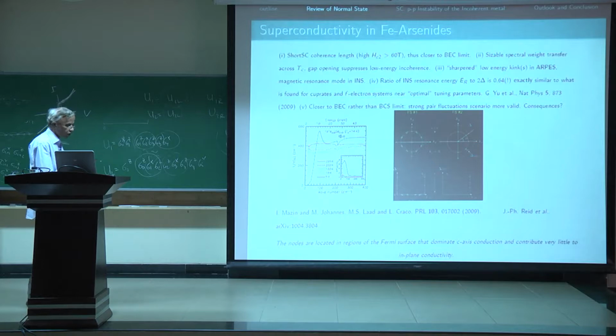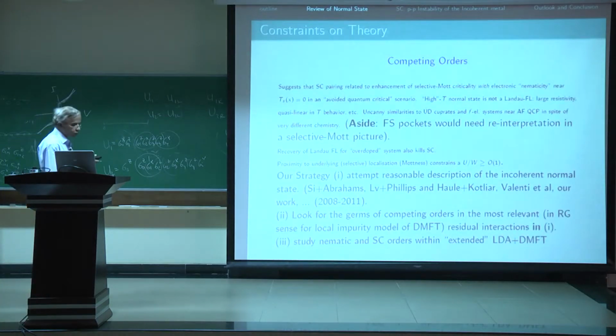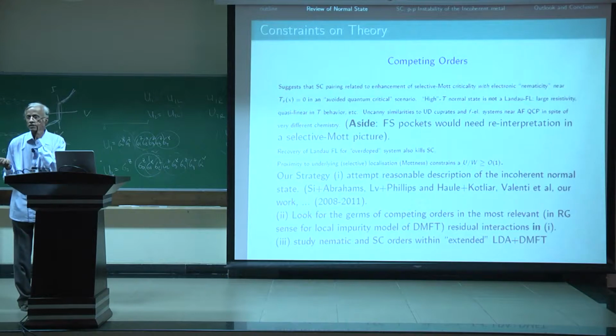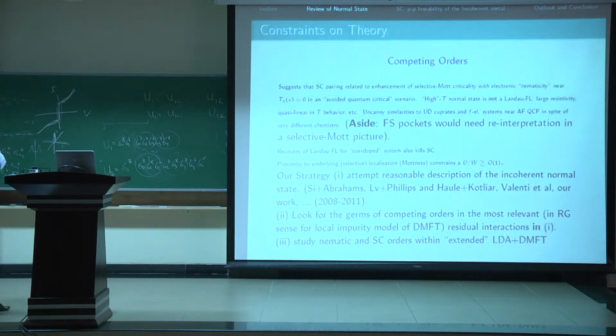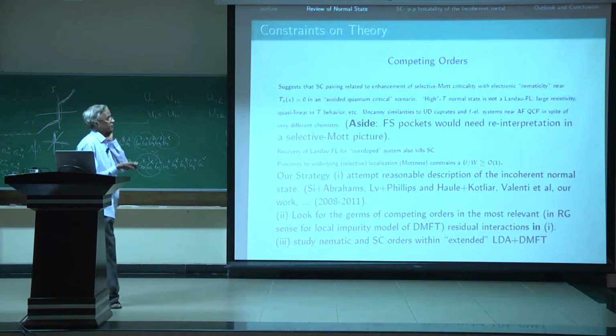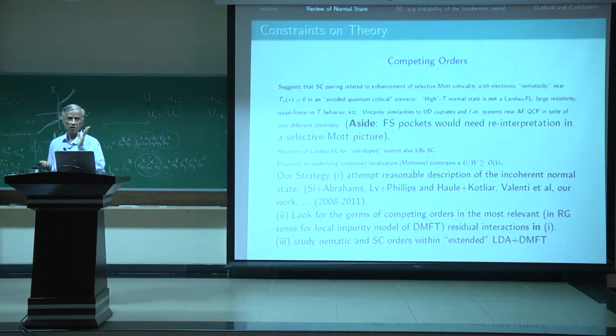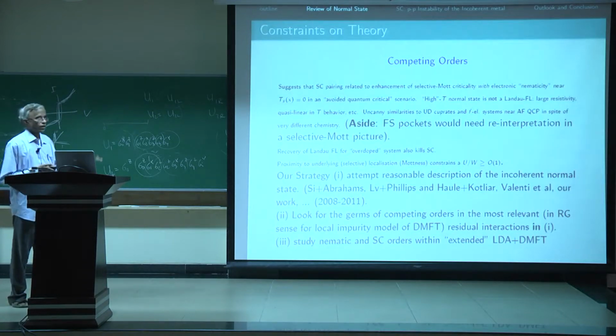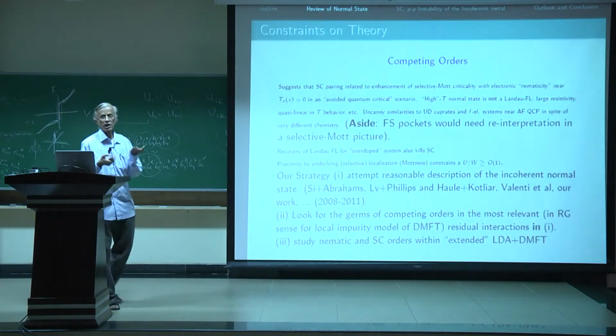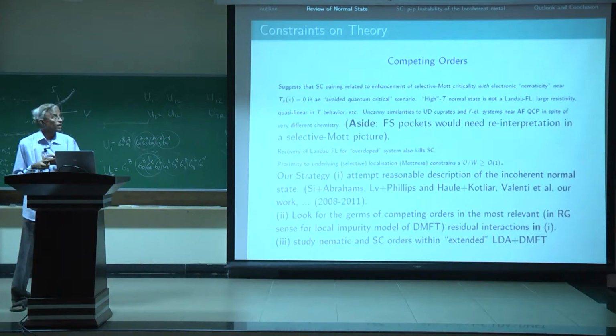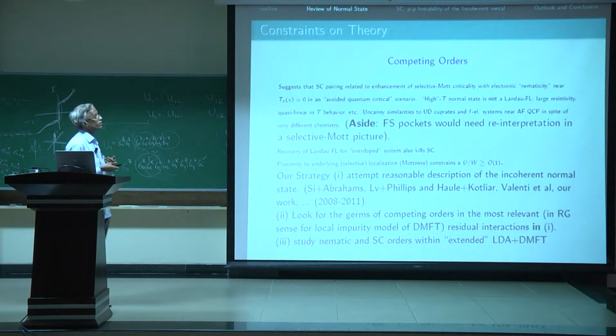Okay. So all these basically put you in a regime where the normal state is incoherent, suggesting sizable correlations, giving way to unconventional orders which either break the four-fold rotational symmetry of the square lattice or give rise to Cooper pairing. But the Cooper pairing itself is unconventional in the sense that you cannot anymore think of the instability as arising from well-defined Landau quasi-particles, since a lot of data shows that the metal is a bad metal and so should not have Landau quasi-particles.